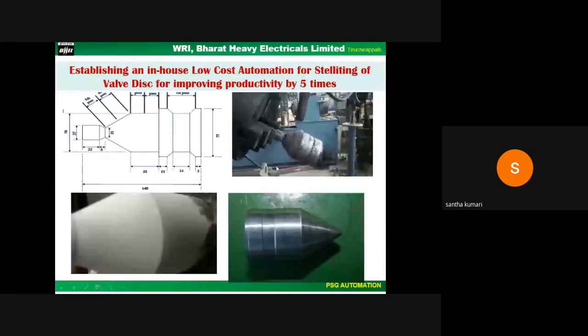It required nearly 25 passes per layer to complete the overlay by the manual TIG process, whereas with this flux cored wire, we use only 6 passes and a minimum of only 2 layers. With controlled weaving, we achieved the desired quality. It was also tested and took nearly a shift to complete. For manual metal arc welding, it required two and a half shifts to complete the welding.